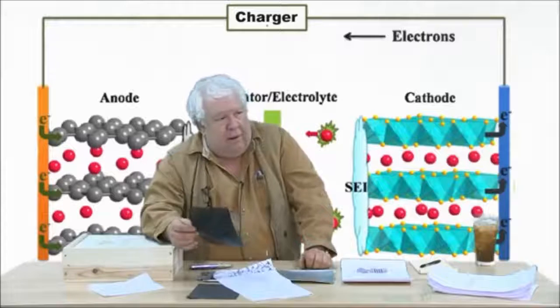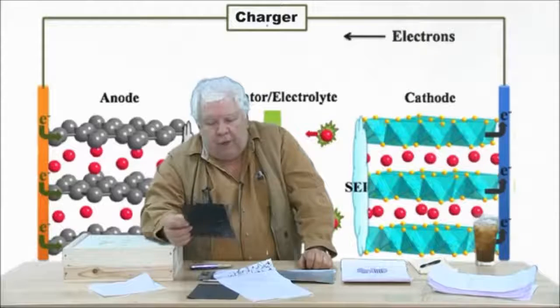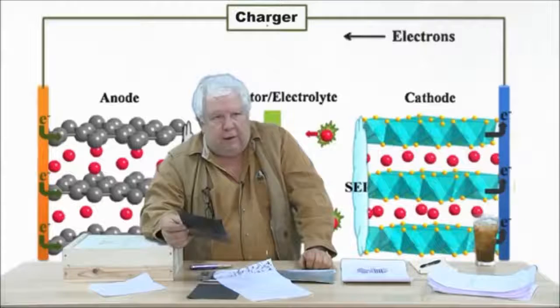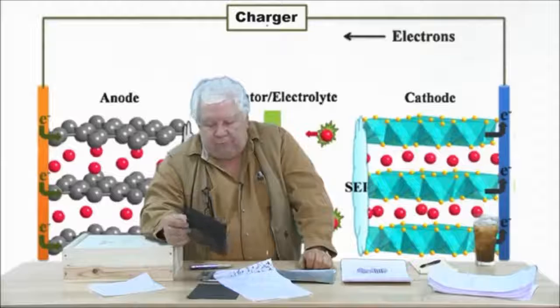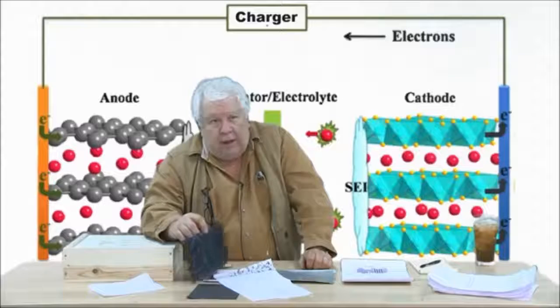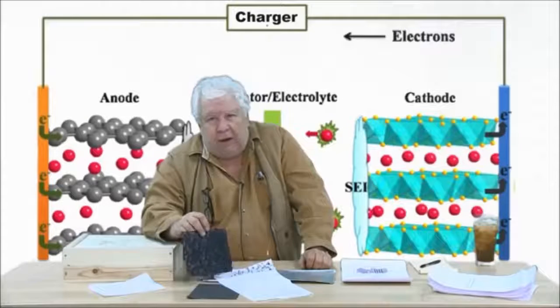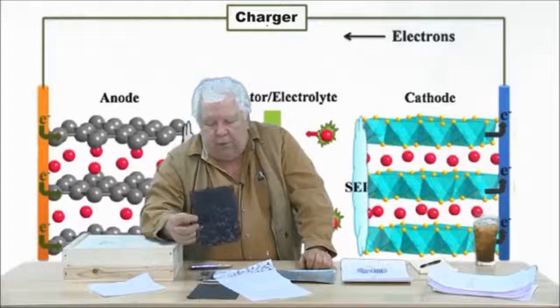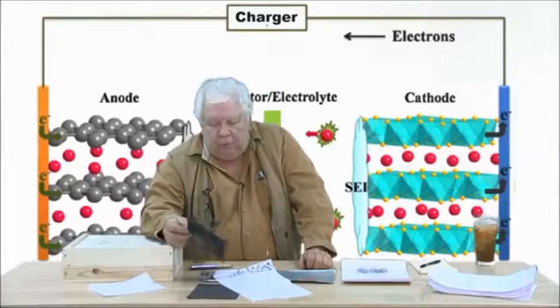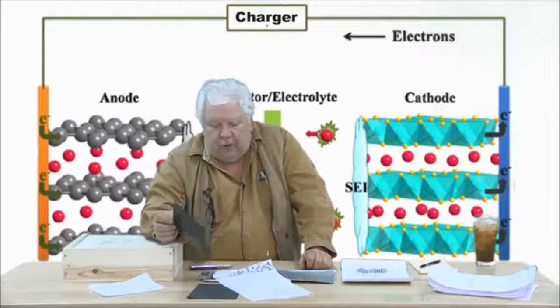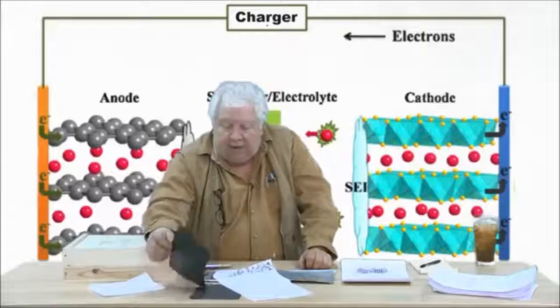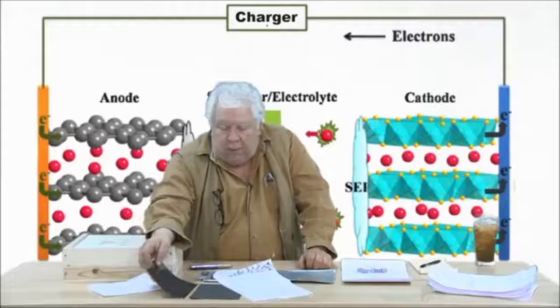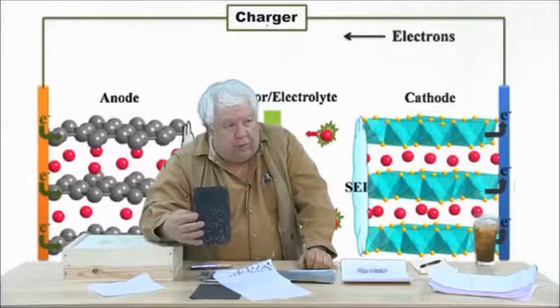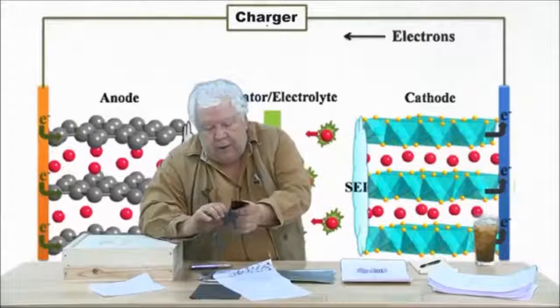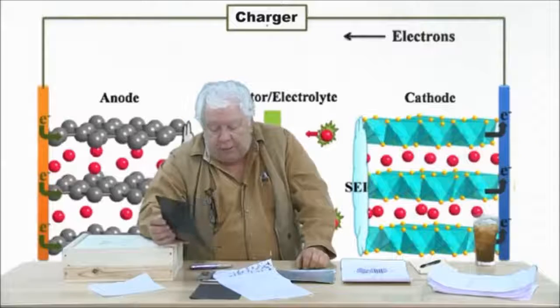in kind of like printing. They put a slurry on it and then they mechanically press it between rollers. This is like in an argon atmosphere. And then they heat treat it and dry it out. The binder is kind of a polyvinylidene material that is sort of like conductive glue, and that's what binds it to that aluminum thing. So that's basically what we have: an aluminum cathode with lithium iron phosphate on both sides, and in this case a little bit of copper, which is why